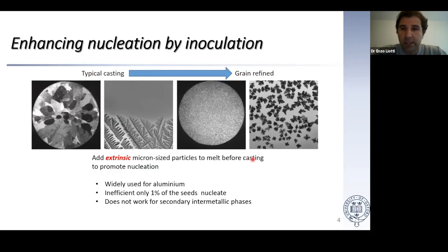And also the inoculation technique works for the primary grains, but it doesn't work for the secondary phase, like the intermetallic phase. So any improvement in the efficiency, even increasing the efficiency from 1 to 2%, or finding a grain refiner for intermetallic phase, would have a very strong effect on improving the material and component properties.